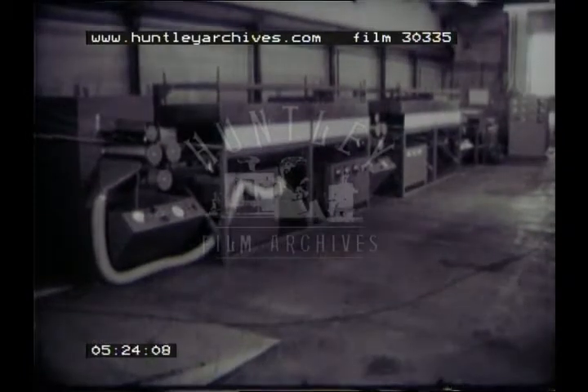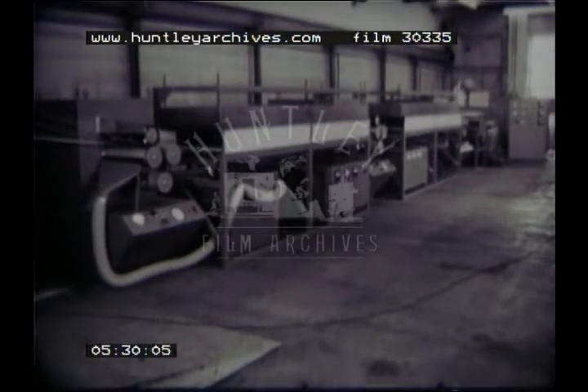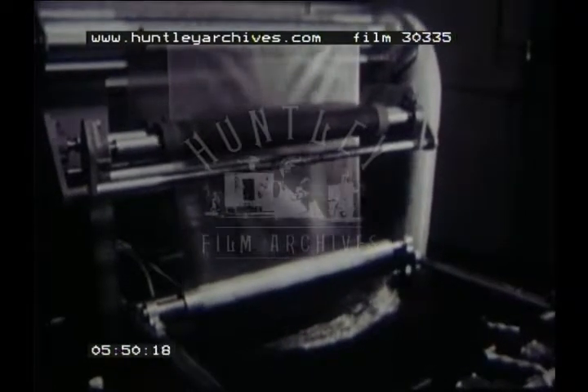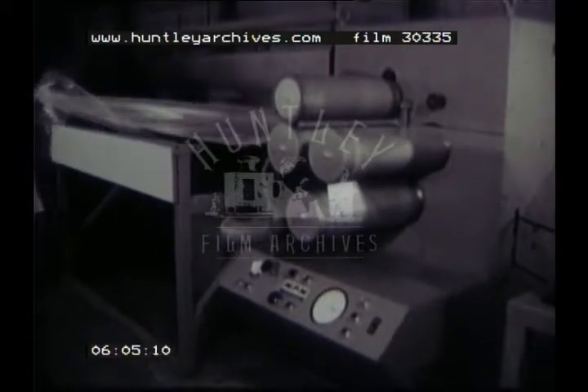Let's return now to look at the simplicity of the operation in more detail. The raw material is raw plastic polymer, a byproduct of the petrochemical refining industry. These pellets are fed into a typical extrusion line. The plastic goes through a die and comes out as film at any required thickness. The cooling bath at a controlled temperature enables crystallizing of the mixture to take place. The resultant film is gripped by nip rollers and fed into a heated oven. The stretch ratio is 7:1.